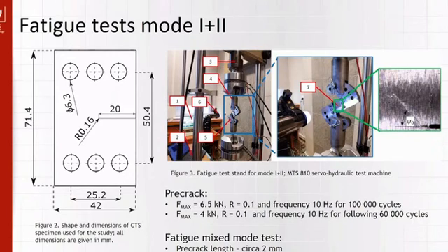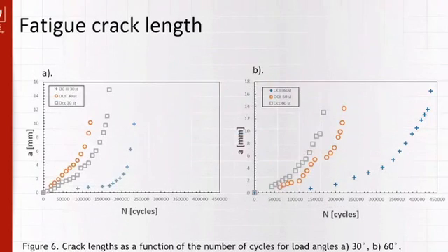Initially, a pre-crack was made under experimentally derived conditions that allow us to achieve a pre-crack of around 2 millimeters long. Later on, the actual fatigue mixed mode test was conducted. The first result that I would like to show you is a simple influence of the fatigue crack length. As you can see on both charts, the crack lengths are shown as a function of number of cycles for both 30 and 60 degrees. What is expected and visible in this chart is that for the 60 degrees loading angle, the life cycle of the sample is longer.